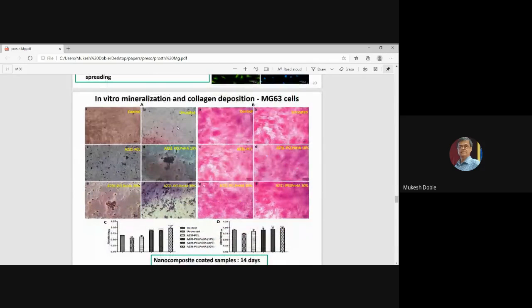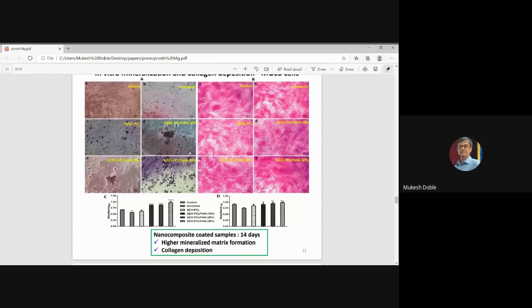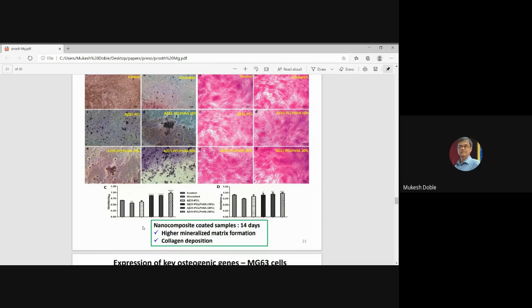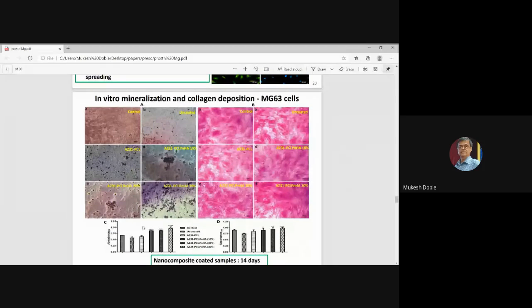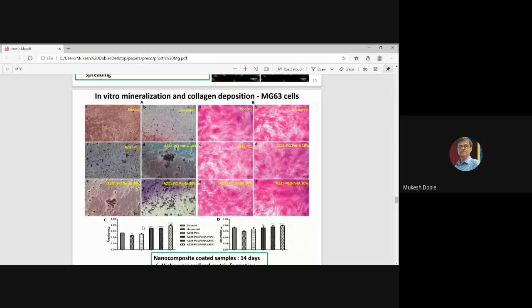These are collagen deposition. So as the mineralization takes place, collagen gets deposited. After all, collagen is part of the bone matrix. Okay? And so you need to understand how the collagen gets deposited with different coated surfaces, with different hydroxyapatite coated surfaces. The pictures here show it with different dyes, and the bar graph shows the quantitative data of the mineralization. So you can see with the good mineralization that's taking place, good collagen deposition is also taking place with the coated surfaces actually. So the in vitro studies show that on the hydroxyapatite coated magnesium surfaces, collagen gets deposited, the alkaline phosphatase activity is also very good, the mineralization is also extremely high.